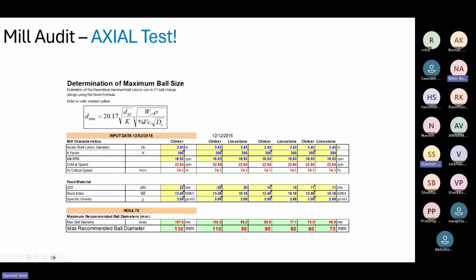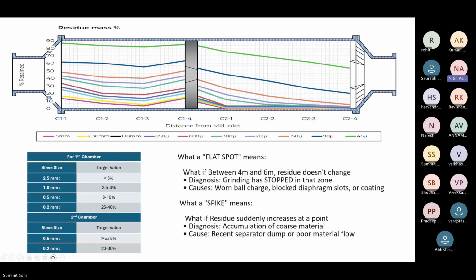Now, Samir sir, in the intermediate diaphragm, suppose anyone wants to go and check whether grinding is okay. So generally, what is the thumb rule? What residue do we have to get at the intermediate diaphragm at 45 micron? There is no number for 45 micron because the material is still very coarse at the first chamber. So we don't do 45 micron. We go ahead with the 2.5 mm sieve in the first chamber.